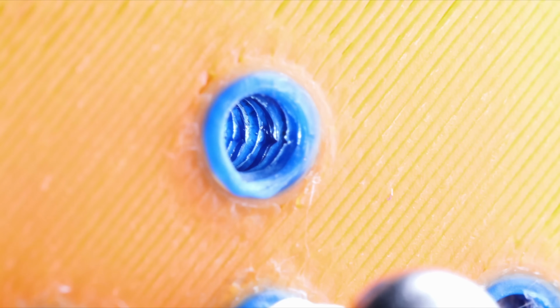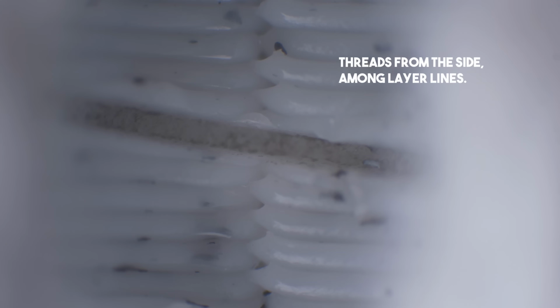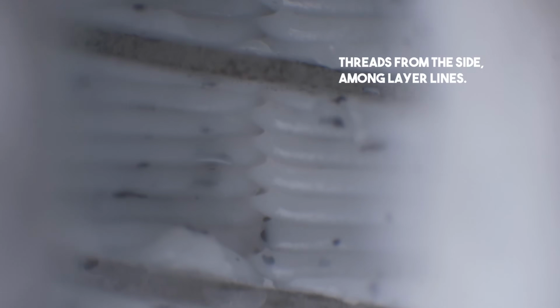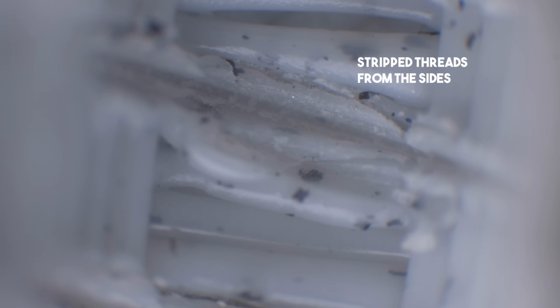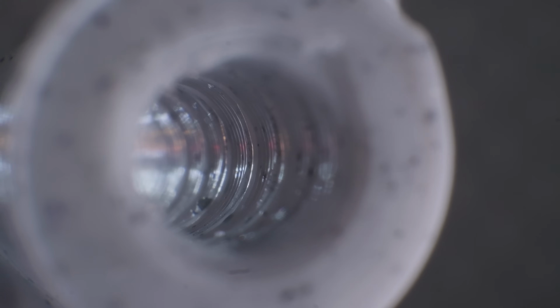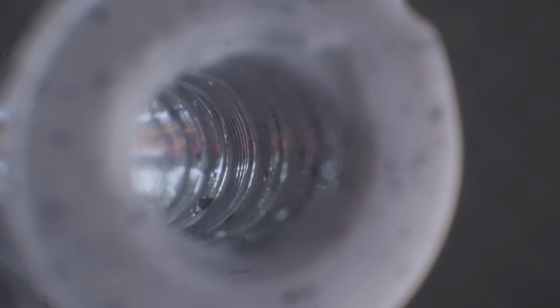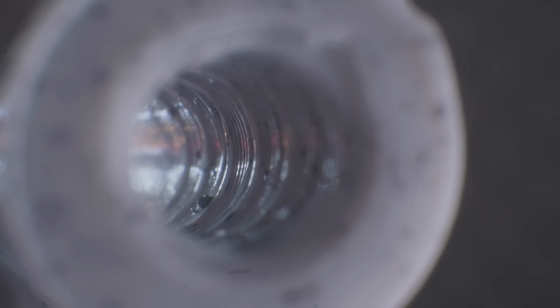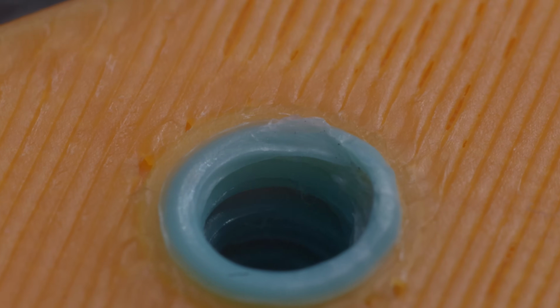I can't prove what's happening at that interface between the threads and the plastic, but here's what I can say. None of the samples showed any stress-based fractures. What I think, and this is a think, is that heat is allowing the plastic to flow into the threads rather than fracture under stress. There might also be some localized stress relaxation at the interface, and this is down to the heat that's being generated by the screw. The possible glazing effects that I observed could be consistent with this, or it could just be an artifact of the way I'm looking into the screw thread.